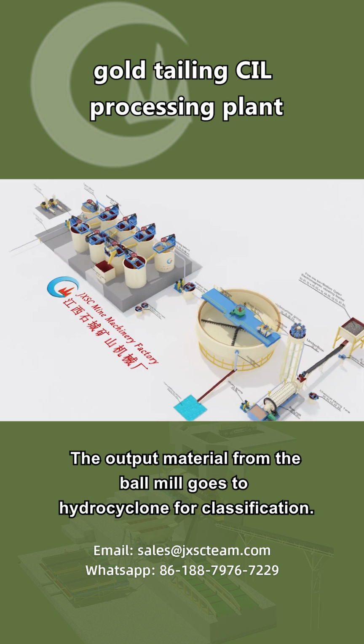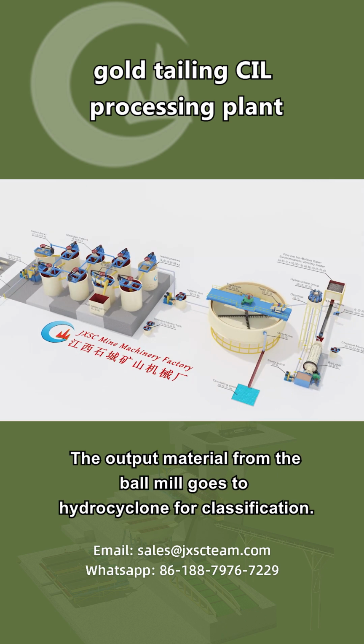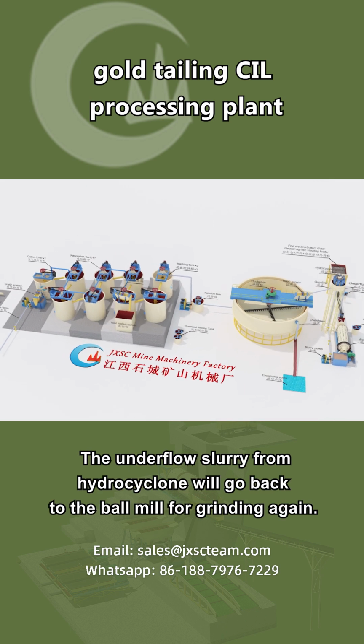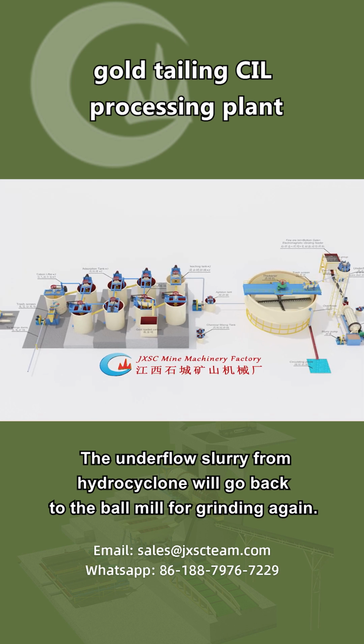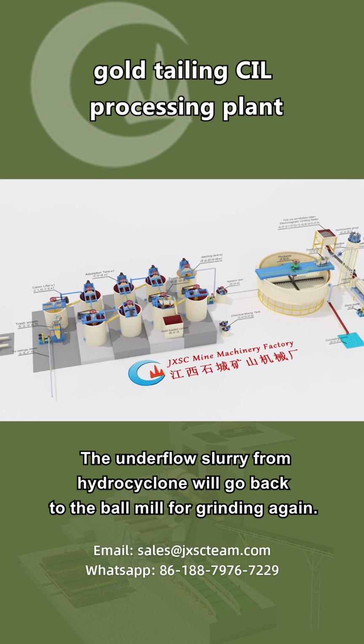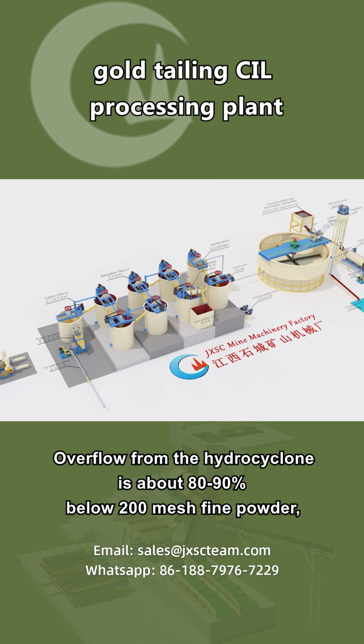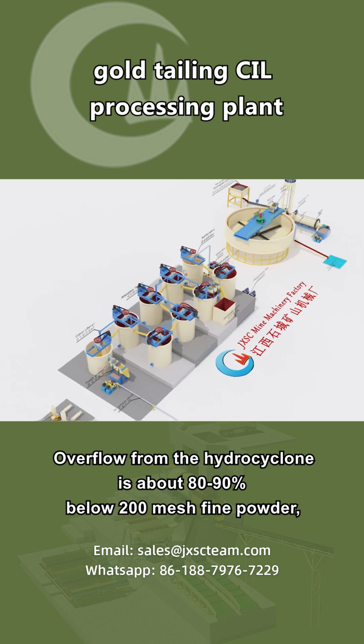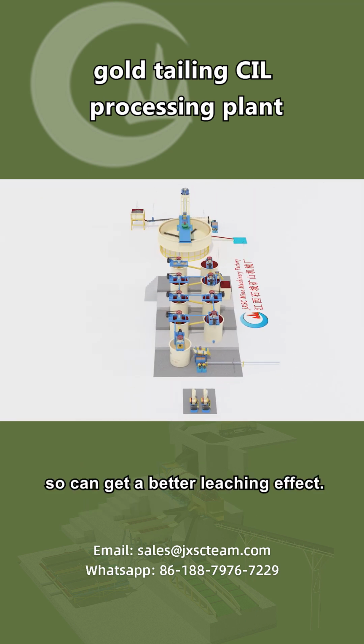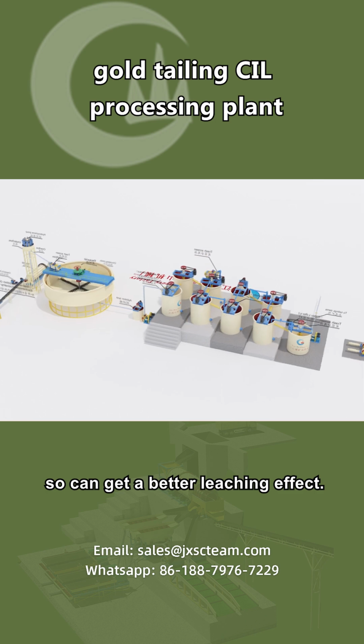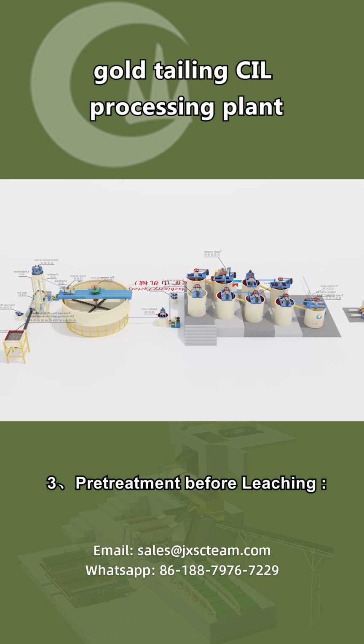The output material from the ball mill goes to hydrocyclone for classification. The underflow slurry from hydrocyclone will go back to the ball mill for grinding again. Overflow from the hydrocyclone is about 80 to 90% below 200 mesh fine powder, so can get a better leaching effect. 3. Pre-treatment before leaching.